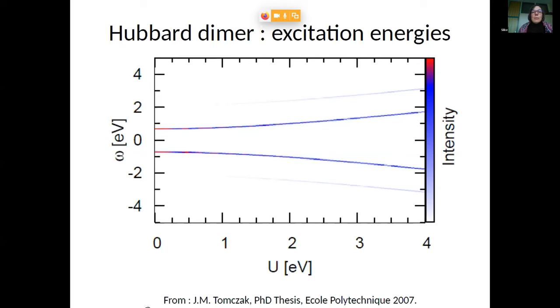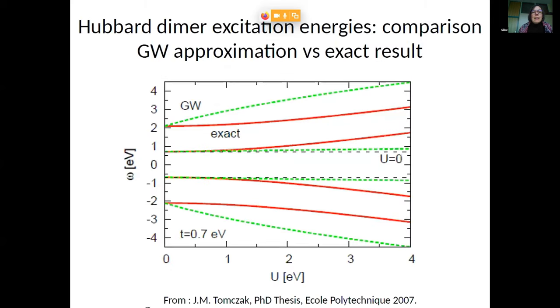And you can ask what GW is doing for that. So this is now a plot where we don't have the intensity anymore, but we have the location of the peaks. So the red curve is the exact. So again, bonding, antibonding here and here. And the green curve is what GW does. And what you see is that indeed, it gets correctly the fact that you have these four peaks. It is having the bonding antibonding splitting essentially set at the non-interacting value. So there's a very, very slight dependence only on U, which means that at large U's, it is underestimating the bonding antibonding splitting. But it also, and that is probably more serious, relatively strongly overestimates the energy of the satellite.